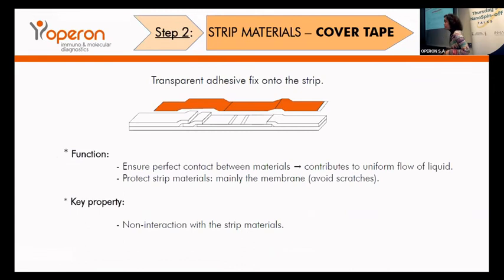And finally, we would like to comment that sometimes it is not mandatory, but in OPERON we usually use a cover tape, which is a transparent adhesive fixed onto the strip, so it ensures perfect contact between the materials and the capillary flow, and also protects the strip materials, because the membrane is really a fragile material. So again, no interactions between the adhesive and the strip materials are required.